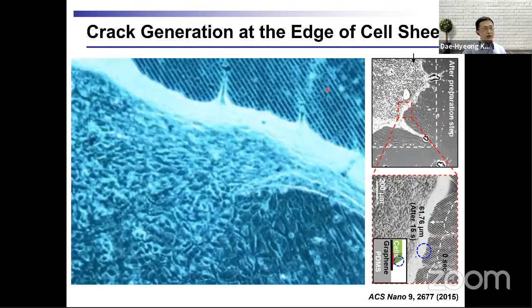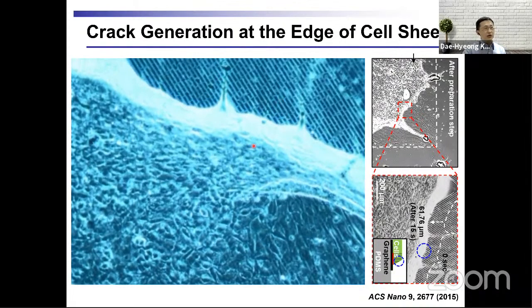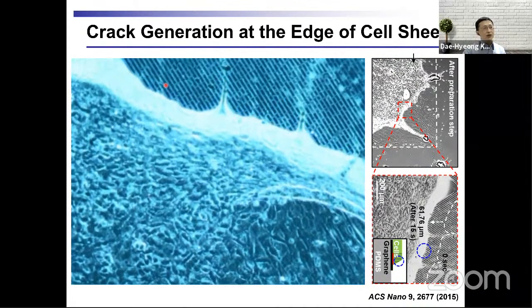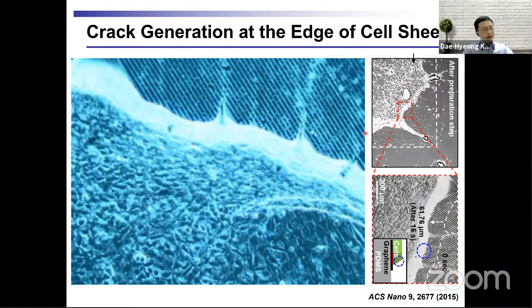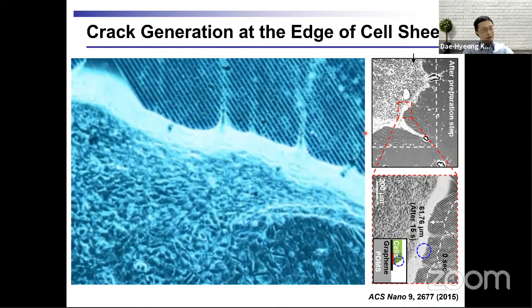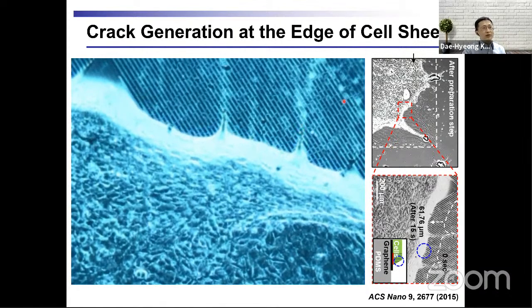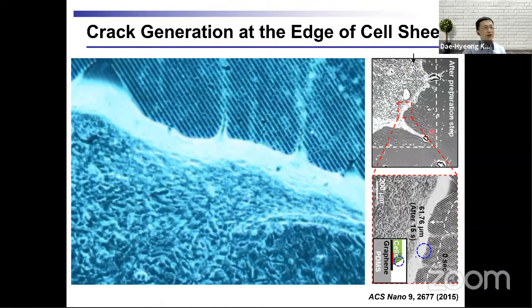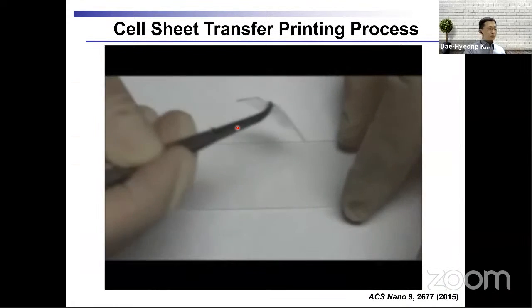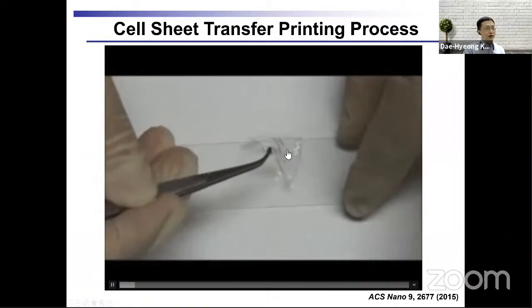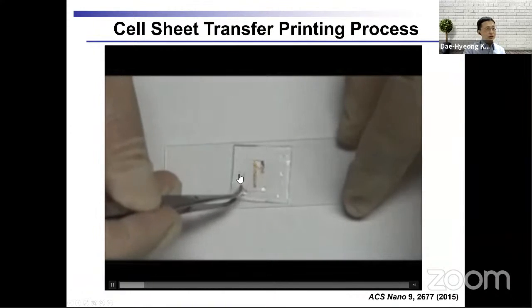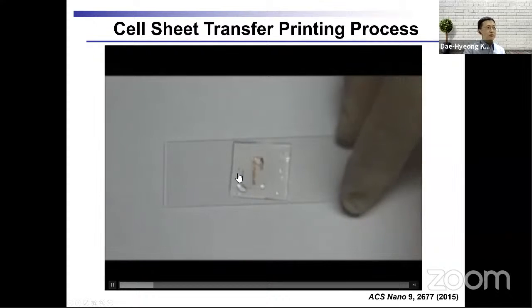This movie shows the crack generation, a magnified view of the edge part of the cell sheet. After making a contact of the cell sheet to the plastic substrate, if we detach it, then a crack will be generated at the edge of the cell sheet. The cell sheet will shrink a little bit, and we can see the crack generation through this movie. Then the cell sheet is ready for transfer printing, and we can make a conformal contact to the target substrate. In this case, we used protein-coated glass.